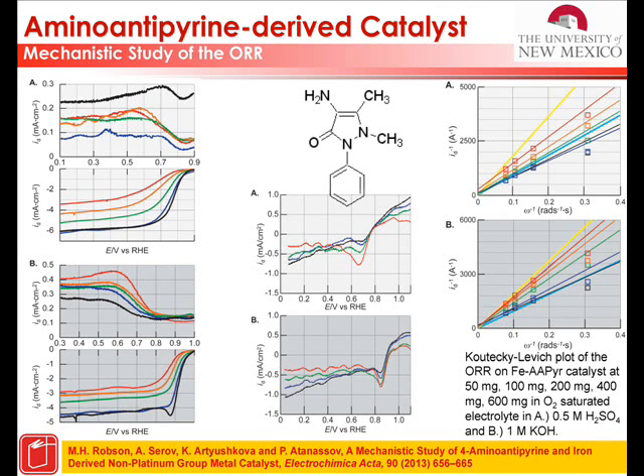Then you test it, and it is truly active, not only for oxygen reduction. Yes, it does produce 1 to 5% peroxide, but it is very active for peroxide reduction as well. And then you optimize this catalyst. You actually see how, depending on the catalyst loading, you move from a 4-electron formal towards 2-electron formal when you decrease the loading. That means that the catalyst really works in a bifunctional mechanism. When the catalyst is a very thin film, the peroxide can escape. When the catalyst is a thick film, it also reduces peroxide inside the catalyst.